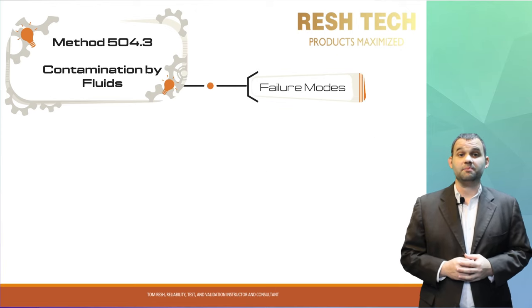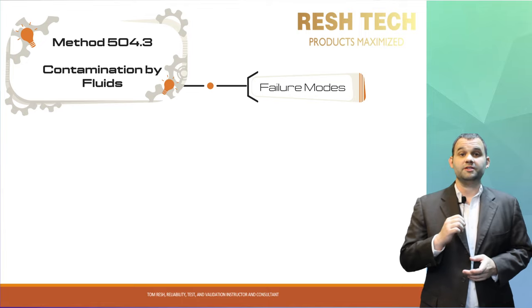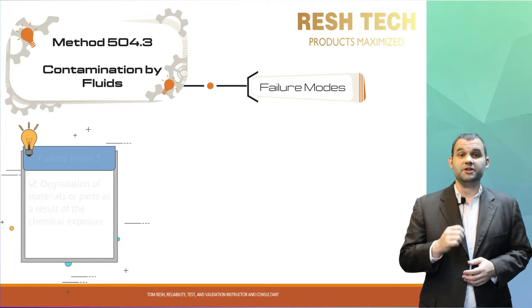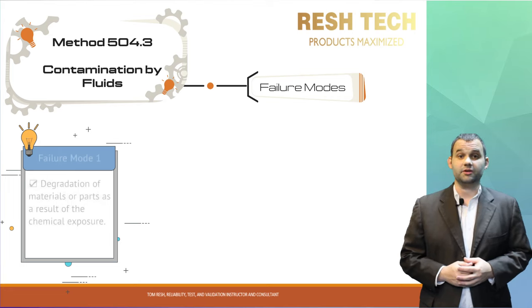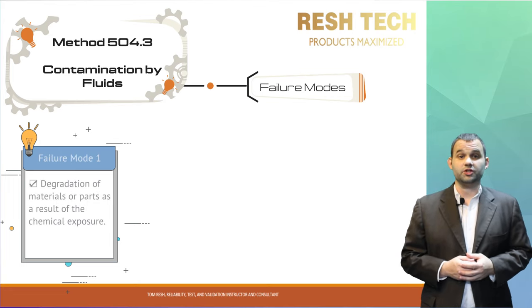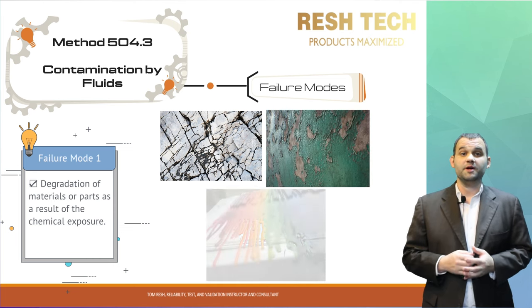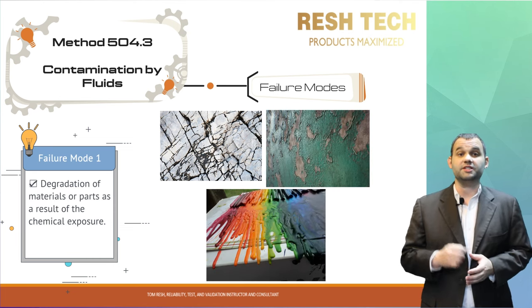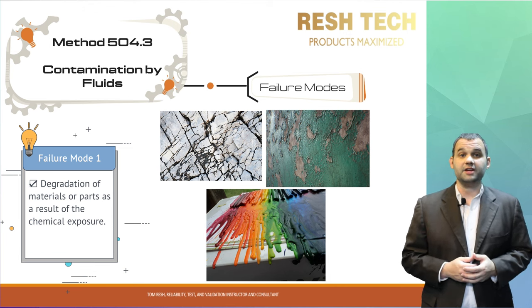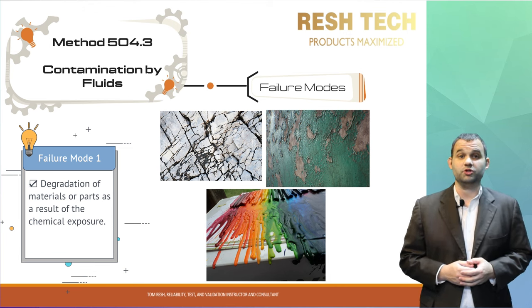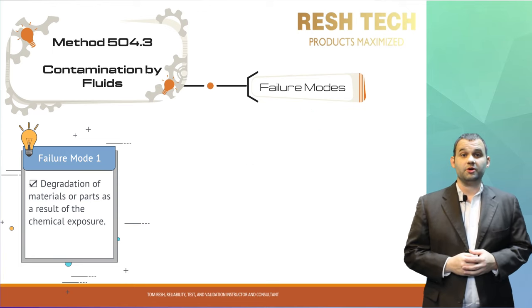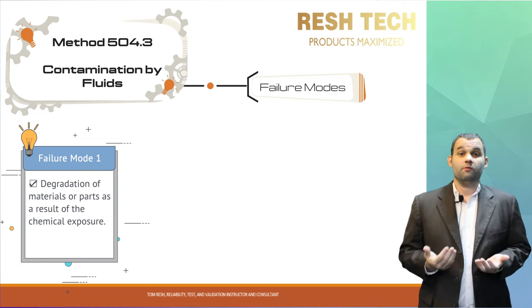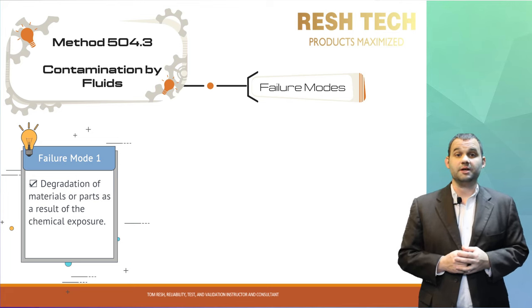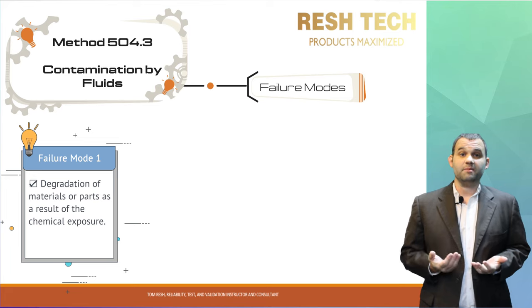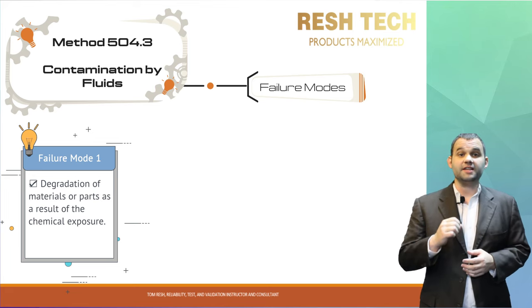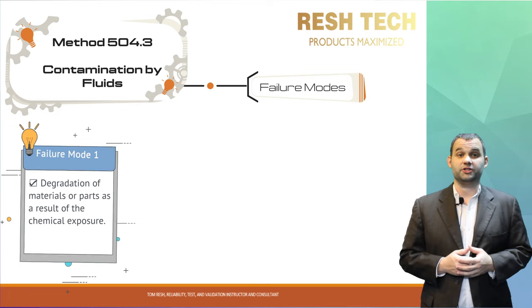Let's cover contamination by fluid failure modes now. The first potential failure mode is major degradation or damage to a system's materials. Chemicals can cause materials to crack, shatter, lose sealant, warp, melt, and so forth if the material exposed is not compatible with or has a reaction to foreign chemical contaminants it is exposed to in the field. Also, look out for chemical incompatibilities with coatings of materials. For instance, you may have a coating on a metal substrate to prevent corrosion, but a chemical incompatible with the surface coating can cause it to crack, flake off, or even melt off.